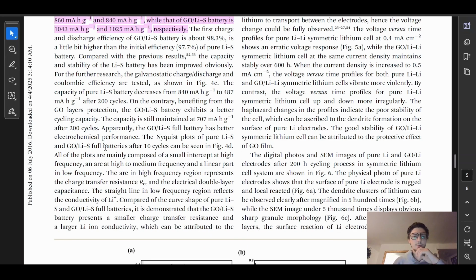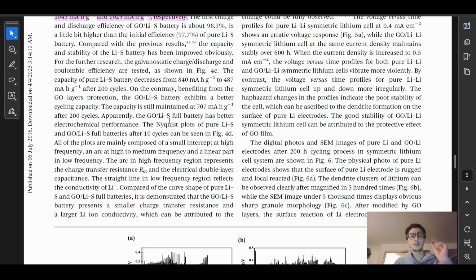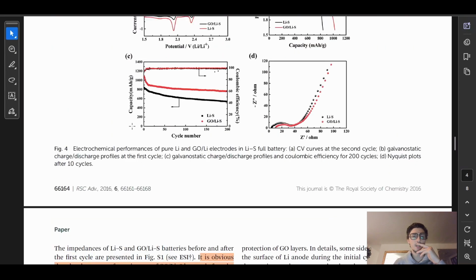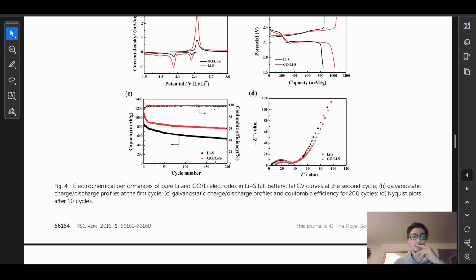After 200 cycles, apparently, the graphene oxide lithium sulfur full battery has better electrochemical performance. Let me put this back in my original orange. I think they're saying it is because they see this red as being higher than this black. So their modified graphene oxide lithium sulfur battery performs better in the coulombic efficiency and better in the capacity after 200 cycles compared to the lithium sulfur one.